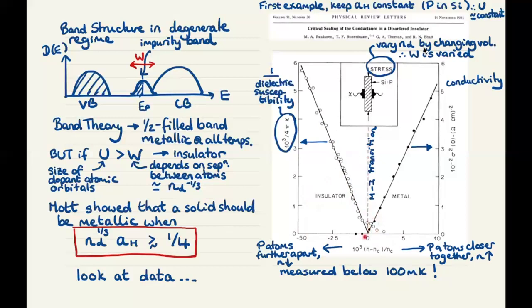At first, it's a rather bad metal with low conductivity, but then as the atoms are pushed closer together, the conductivity is increasing as it moves more into the metallic regime. And again, to emphasize here, this is all the same system. It's phosphorus atoms in silicon. So the hydrogenic radius and the Coulomb repulsion between the electrons are kept constant, and all that's varied is the dopant concentration.